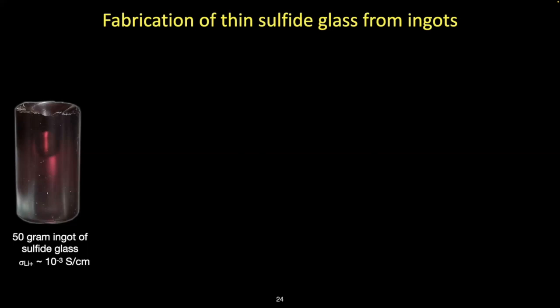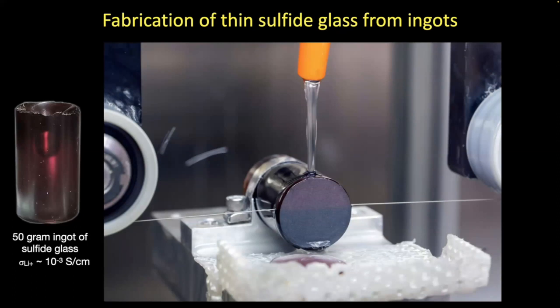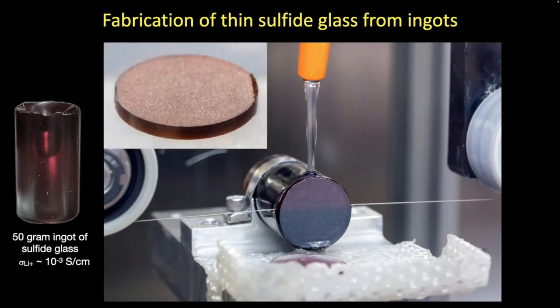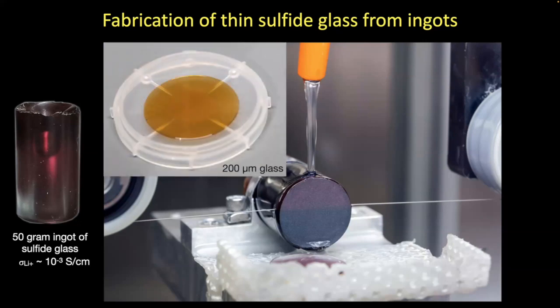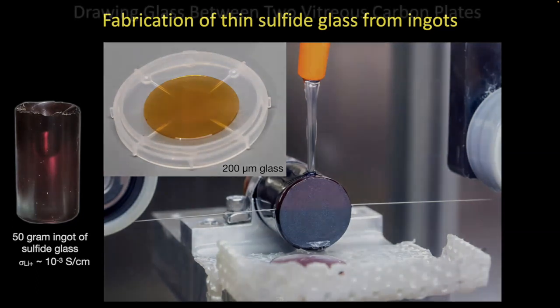So the actual fabrication occurs something like this. What you see on the left is a 50 gram ingot of high conductivity sulfide glass. We have another company that's producing that for us, and they ship material to us on a monthly basis. And that can be cut. Here you can see we can cut that into discs that are pressed into discs for electrochemical testing, or we can convert this to a preform, and you'll see that as well. Here we're using a wire saw to cut out a disc. That's a rough cut disc, and then we can warm that above the glass transition temperature and simply press it into a solid electrolyte, again pinhole free, fully dense, and then build cells with that.